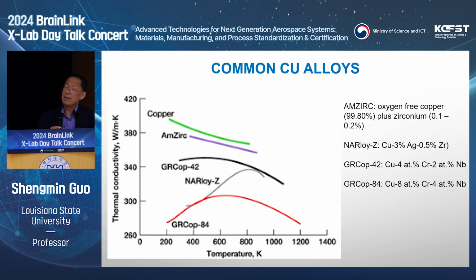Yeah, pure copper gives you the highest thermal conductivity, right? It stands a chance to take heat away. However, pure copper is not strong enough. When you heat up to a slightly elevated temperature, the copper will lose strength. The goal of this NASA copper alloy GRCop-42 and GRCop-84 design is to find copper alloys which can give you good mechanical strength